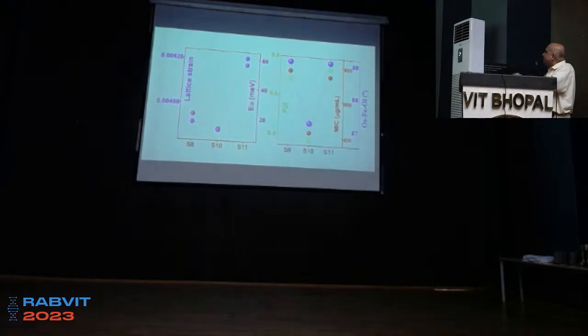So whenever you make your sample, please keep this in mind, that just by making a sample, it does not mean anything until and unless you understand what is going on behind. Now, this is the correlation. We also studied the bond angle and bond length, and we found that one specific bond length, a bond angle, is very important, and it is matching with the MIC trend and also the PTI trend. So there is some correlation between these three parameters. This is somewhere we have got stuck right now, and we are investigating further.